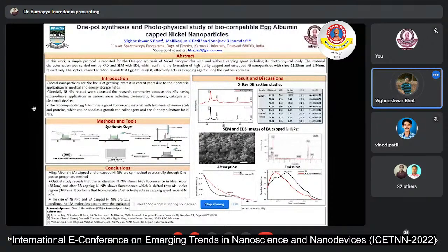By using SEM analysis, the morphology of the nanoparticles is studied. Here, in order to get distinct particles, the images show that spherical shaped nanoparticles are formed. But because of poor resolution, I didn't get a clear image of the spherical shape. By improving the resolution of the image and using a clear SEM pattern, it is possible to calculate the diameter of the synthesized nanoparticles.